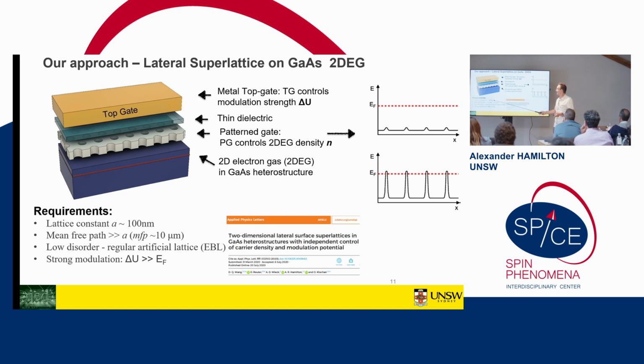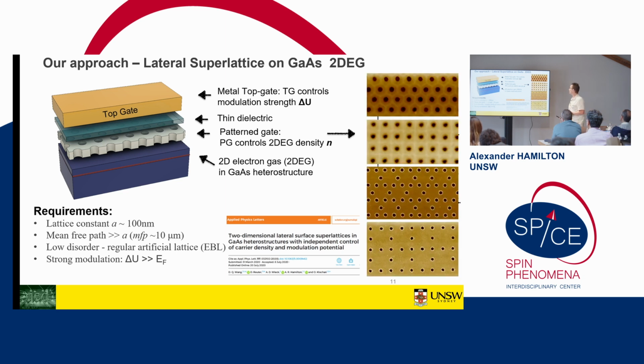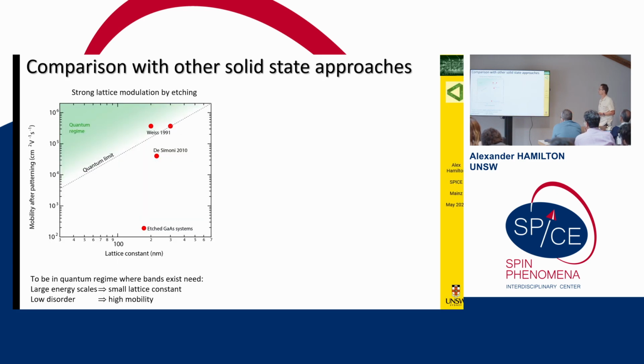And we can create a lattice constant of about 100 nanometers. The mean free path is much, much larger than the lattice constant, so we're in the low disorder regime. We make the lattice very regular, and we can get very strong modulation where this potential is much larger than the chemical potential. And of course, because we're making it with electron beam lithography, we can make any lattice shape you want. We're going to concentrate today just on the triangular honeycomb lattice.